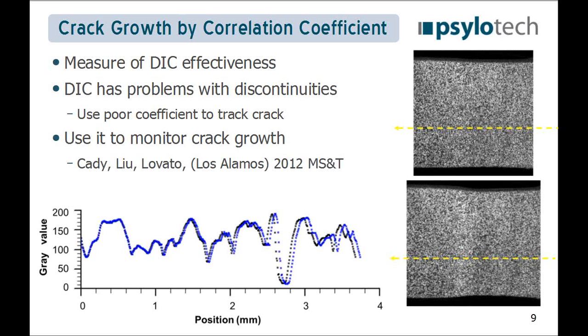So what happens is there's a correlation coefficient, which is a degree of not accuracy necessarily, but a degree of confidence that the DIC is working properly. When that gets too high, you can see that there's a problem, and that very problem can be used to track the crack length. I saw some people doing this back at the MS&T in 2012, some folks from Los Alamos, and I'm sure other people are doing it as well, but that's where I first saw it. So we talked about using the crack tip opening displacement. We talked about using the correlation coefficient to get crack length.